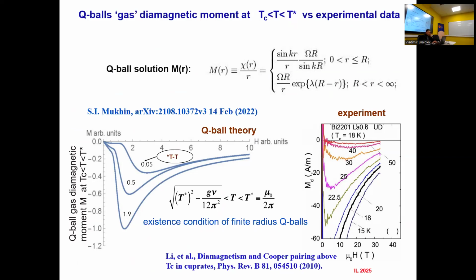what other manifestations of Q-balls. You can also calculate, because if you have a Q-ball with a superconducting condensate inside, it means if you switch on a magnetic field, this Q-ball would have currents which produce a diamagnetic moment. And you can calculate what would be the diamagnetic moment of the Q-ball gas as a function of temperature. And then you see these curves. They're calculated exactly. This is the answer to your question.